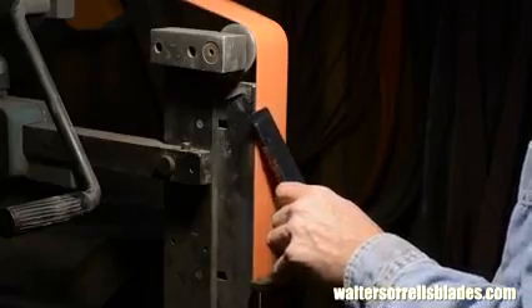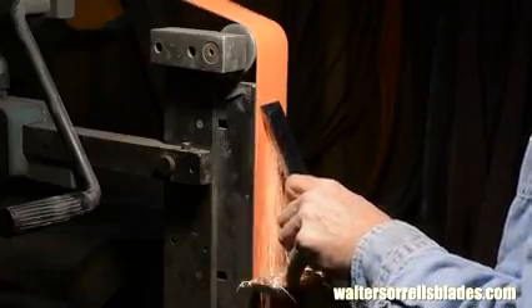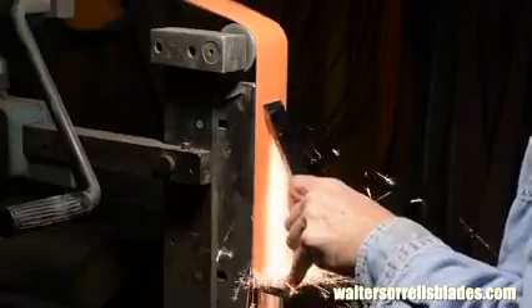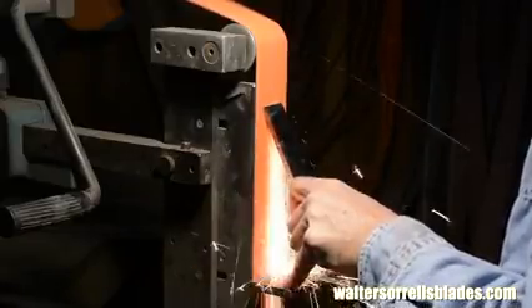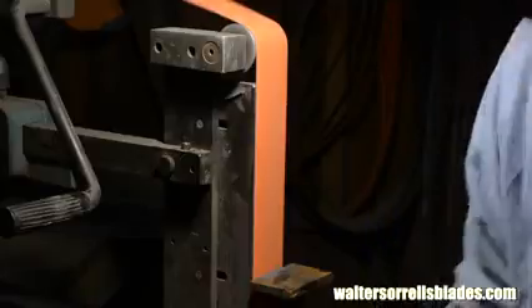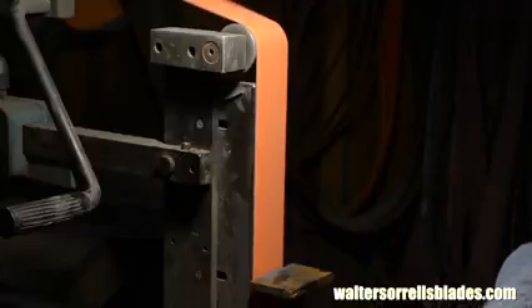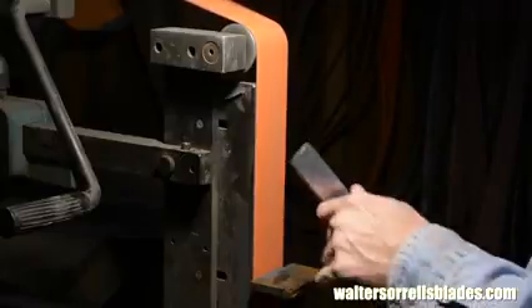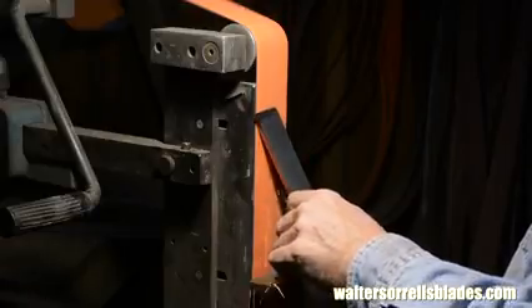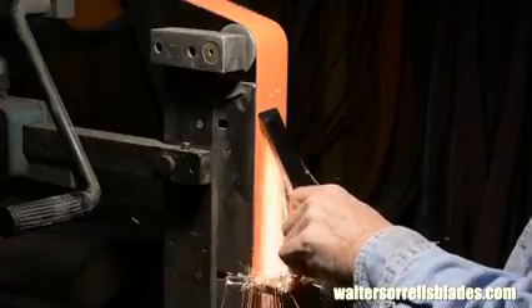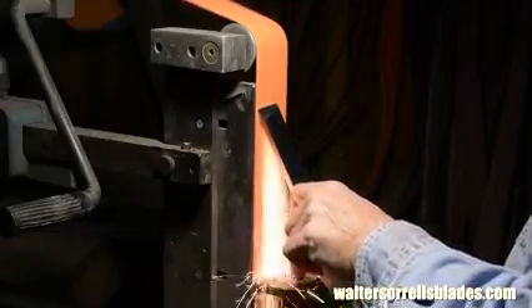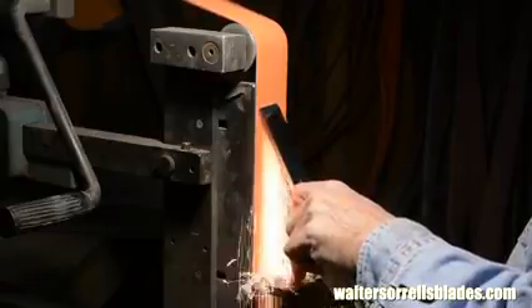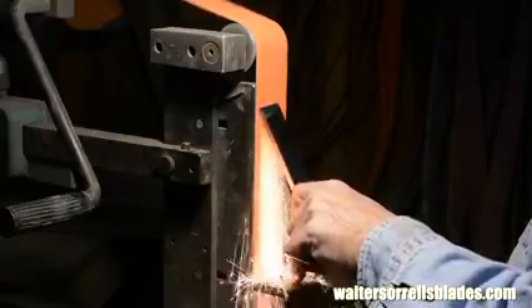Now bear in mind that grinding generates heat. With a big grinder like this, lots of heat. Now that the blade's heat treated, you don't want to overheat the tool, which would cause it to soften your cutting edge. If you see the edge of a carbon steel blade suddenly turn blue due to the heat that you've built up, you've gotten it too hot and ruined the edge, so you'll need to grind that part away and start over.